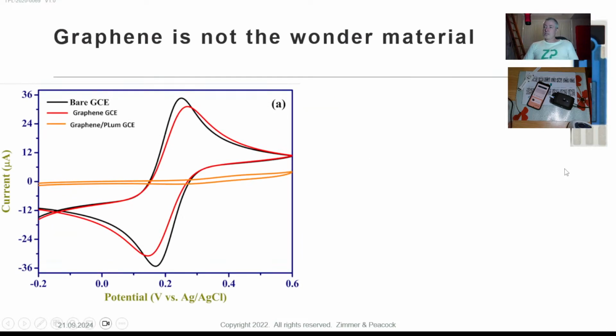Question number 4. This is an interesting one. Another one about cyclic voltammetry. What I found really interesting about this was that there's a bare glassy carbon electrode here, which has slightly higher peaks than the graphene carbon electrode, and they put polyluminol over the electrode, and I'll discuss that in a minute. But what's really interesting is that the graphite electrode has the peak-to-peak separation a little bit closer relative to the graphene. With the graphene, the peak-to-peaks move away from one another, and with the graphite, the peaks are slightly higher, and with the graphene, they're slightly smaller.